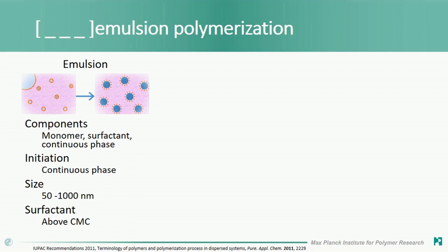So before the polymerization, there's a segregation of the monomer phase that is immiscible with the continuous phase, either inside the micelles or inside bigger reservoirs. And we have some empty micelles too. During the polymerization process, the monomers are insoluble in the continuous phase, but nothing is really insoluble. They will slowly diffuse through the continuous phase, react with the initiator molecule in the continuous phase, and just statistically enter one of the micelles that contain some monomer or not, and then the polymerization reaction will progress.